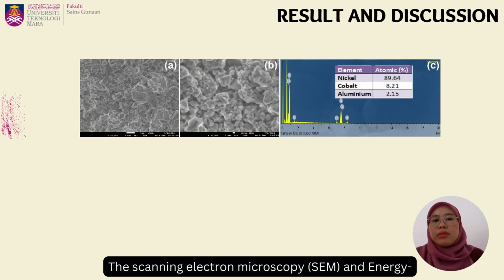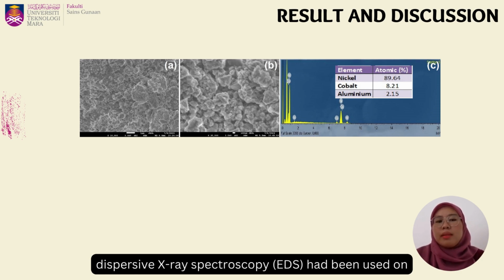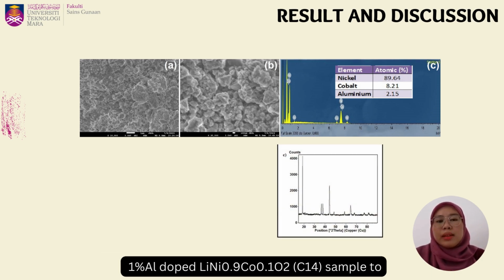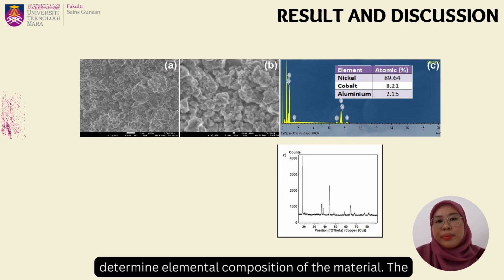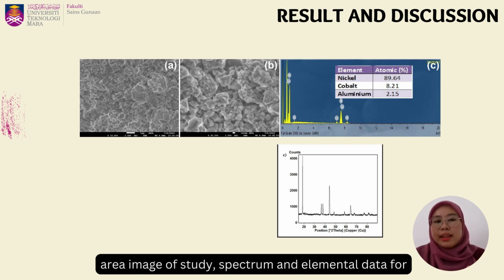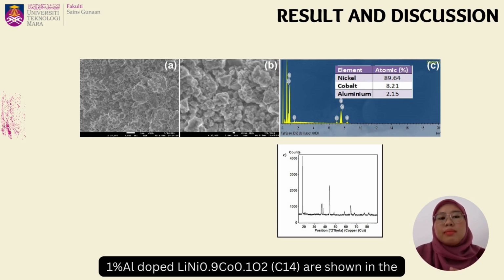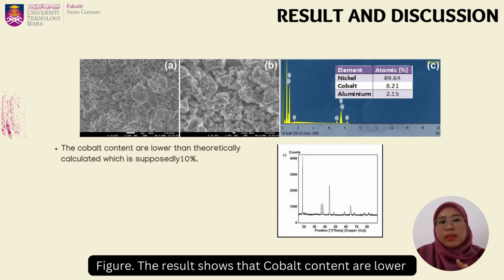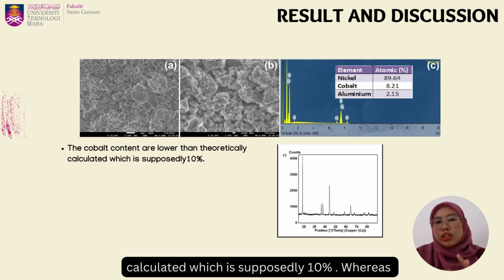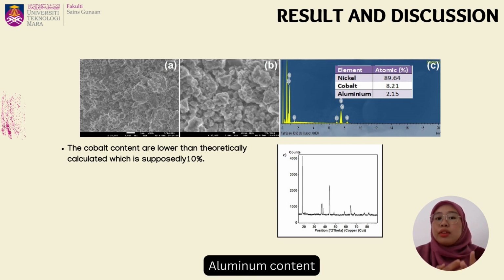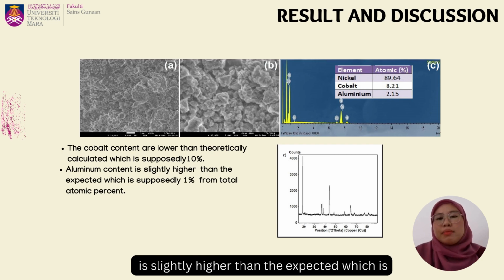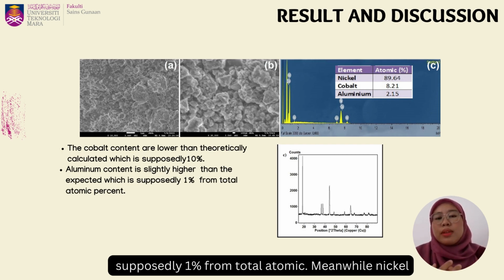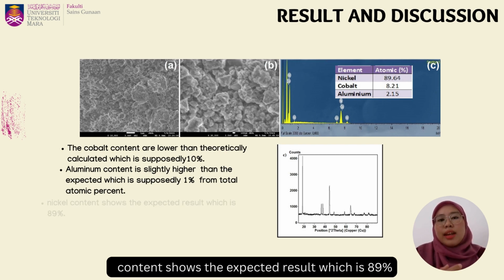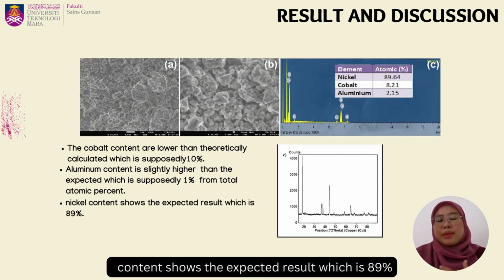Scanning electron microscopy and energy-dispersive X-ray spectroscopy were used on the 1% aluminium-doped lithium nickel cobalt oxide C14 sample to determine the elemental composition of the material. The area image of study, spectrum, and elemental data for the C14 sample are shown in the figure. The results show that cobalt content is lower than theoretically calculated, which is supposedly 10%, whereas aluminium content is slightly higher than expected, which is supposedly 1% of the total atomic. Meanwhile, nickel content shows the expected result, which is 89%.